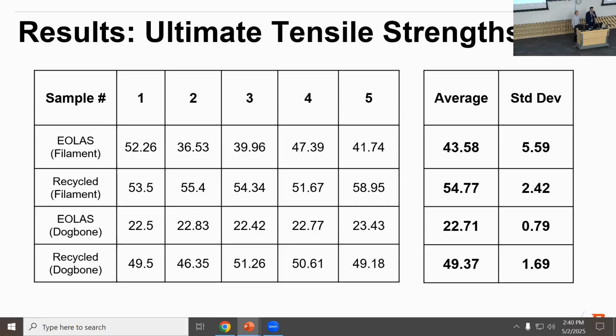far outperformed, by over a magnitude of 2, the dog bones of the pure Aeolus pellets. On top of that, the filament for the recycled was also better than the pure Aeolus pellet filament, and it also had a smaller standard deviation, which means we were able to produce more consistent data with that.